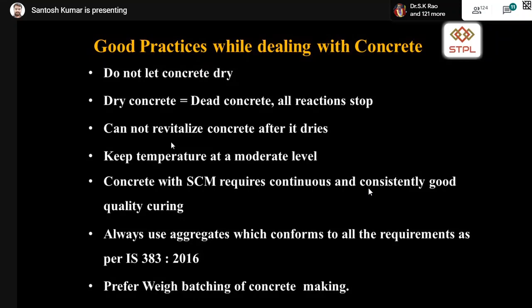Coming to the good practices while dealing with concrete, please remember, don't let the concrete dry. It should be saturated, or it should be cured for a minimum period of 7 to 14 days. When you are using supplementary materials, the minimum curing period should be 14 days. Dry concrete is equal to dead concrete.